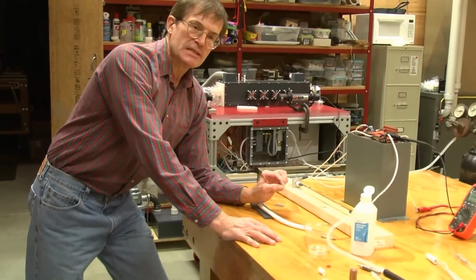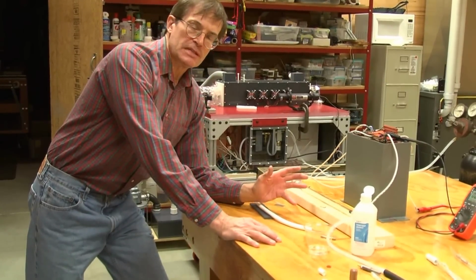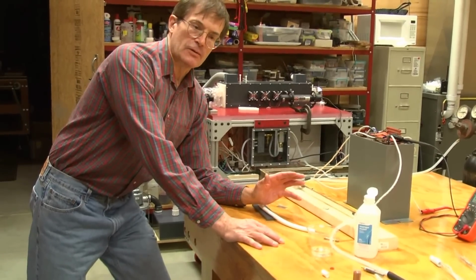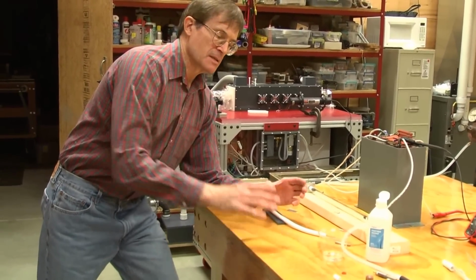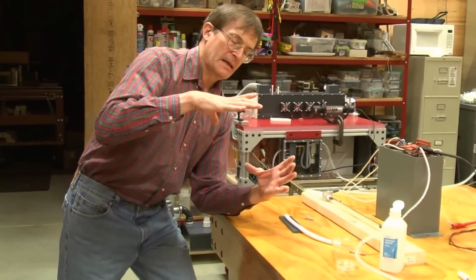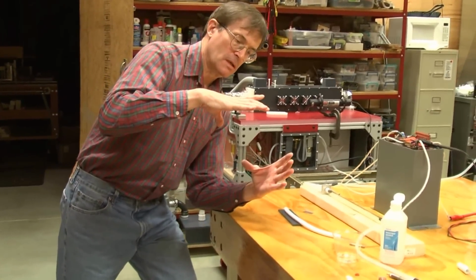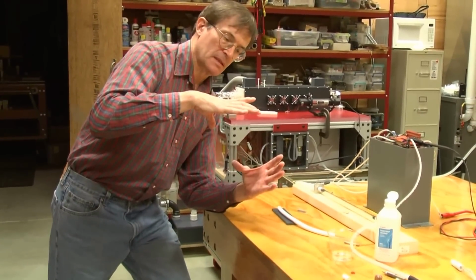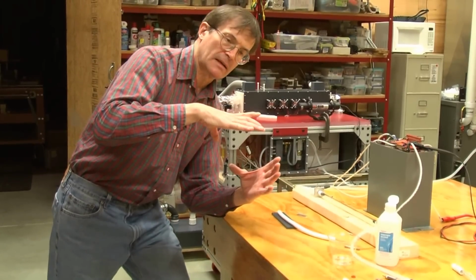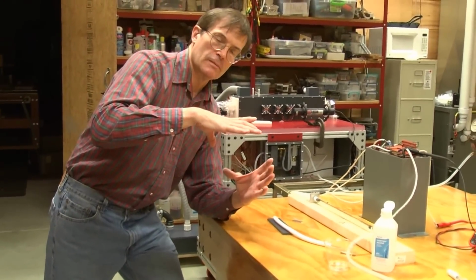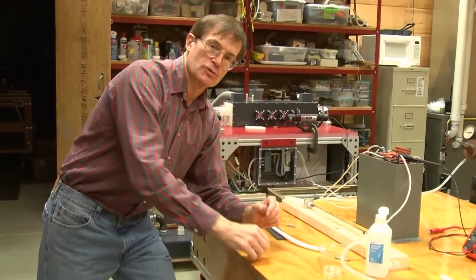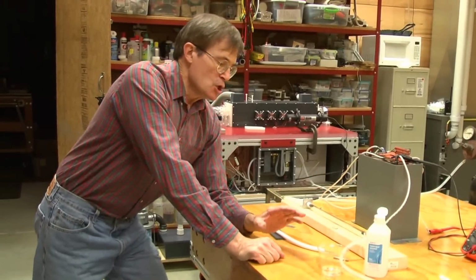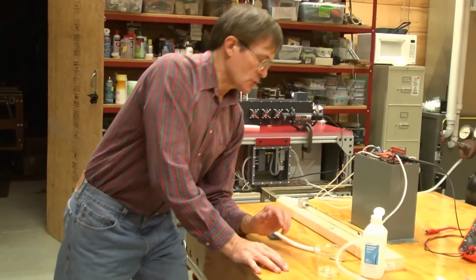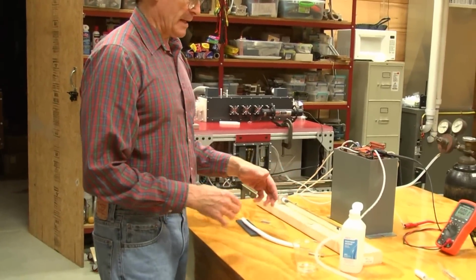It does increase very slightly from about 13 microseconds to about 15 microseconds. And I believe that's because the outer wall that has a thin annular plasma with the silicon and oxygen is actually constricting the low pressure regime a little bit, and that's what's producing the increased resistance. So with that kind of background, I'll show you basically what I do with the lamp once I've set it up.